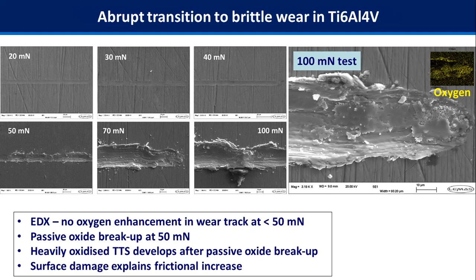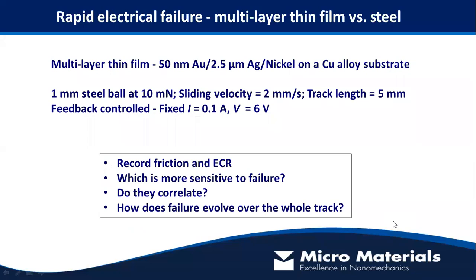However, starting at 50 millinewtons, you get this abrupt transition to a much more fractured surface, which becomes progressively greater at higher loads. So this tribologically transformed structure breaks up the initial oxide, and you create a much more heavily deformed area where there's a lot of tribo-oxidation occurring as well. And this explains the frictional increase. So we'll move on now to the electrical measurements.